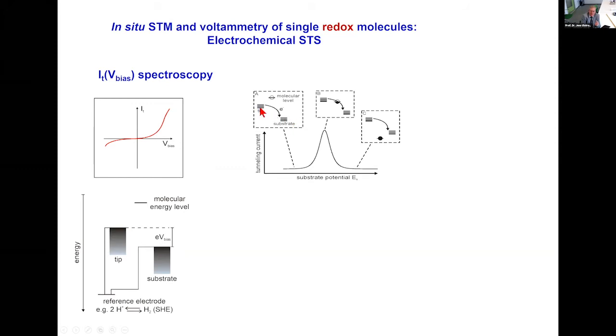That would show us, for example, if we shift the substrate and tip potential up and down in parallel, then as we get closer to the molecular level, the current will begin to rise because the tunneling barrier decreases. But when we raise it far enough, the molecular level is trapped between the two Fermi levels, and then the mechanism changes entirely. Now it becomes hopping, successive electron reduction and reoxidation. In tunneling language, it is as if we dig a deep hole in the tunneling barrier. So this is a very efficient mechanism, and the current rises drastically.